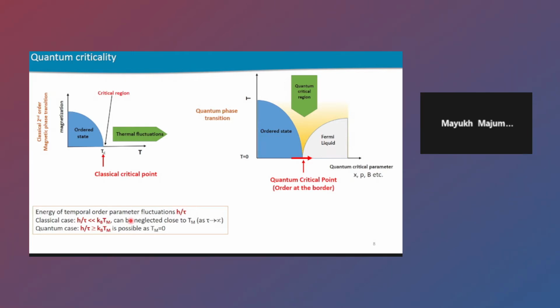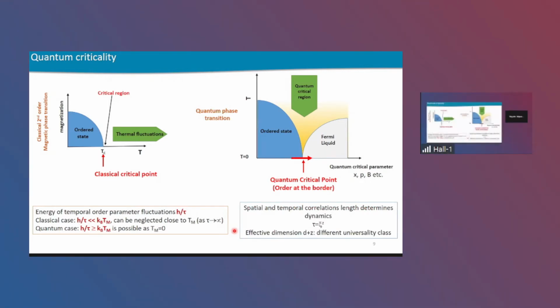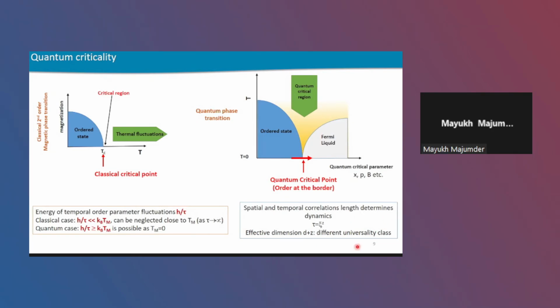But on the contrary, in case of a quantum phase transition, we know that the ordering is at 0 Kelvin, right? So here it is just the opposite: the energy of the temporal order parameter fluctuations is higher than that of the thermal fluctuations. So that incorporation of the effect of the temporal order parameter fluctuations dictates the dynamics of the system. And you get different universality classes compared to the classical second order magnetic phase transitions.